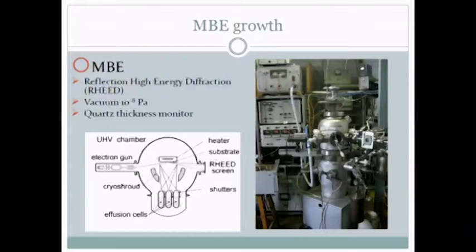So it was prepared in Russia with a molecular beam epitaxy chamber in ultra-high vacuum. Ultra-pure material, lanthanum fluoride and strontium fluoride, was put in effusion cells. Then it was evaporated on top of the substrate, and the films obtained then were studied in different ways.